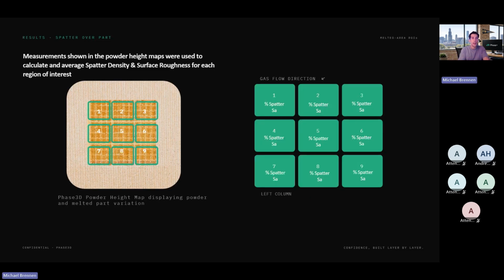So we took a similar approach, and we divided the build volume into 9 regions, and we looked at the same metric that we discussed before, percent spatter. Did the pixel measure above a threshold, and which percentage of the pixels in that region measured above that threshold to give us a percentage. And then we also measured a surface roughness across that region, with our hypothesis being that if there is a higher spatter density or higher spatter percentage, then there would be a higher surface roughness in each of these regions.